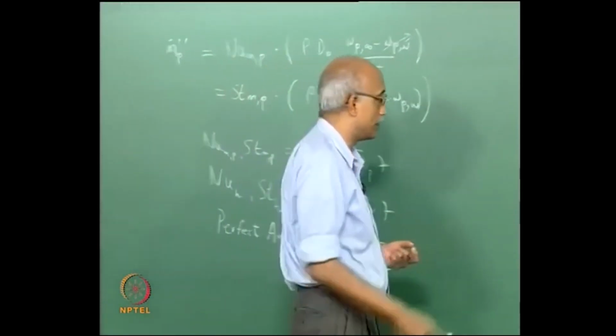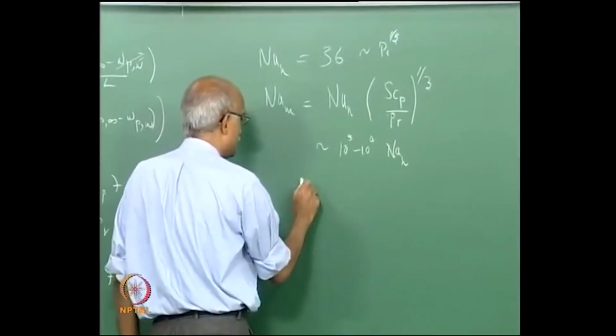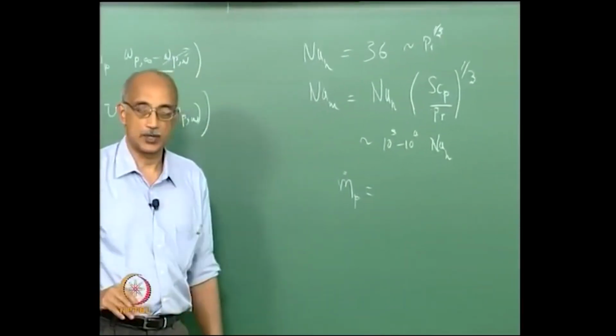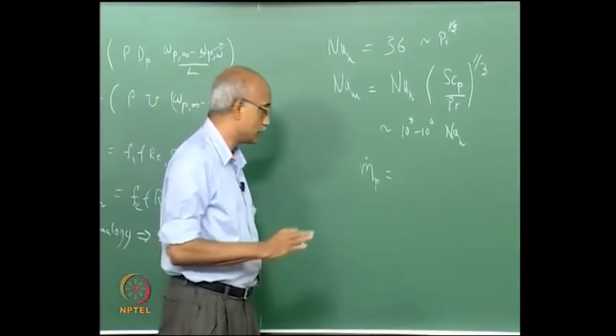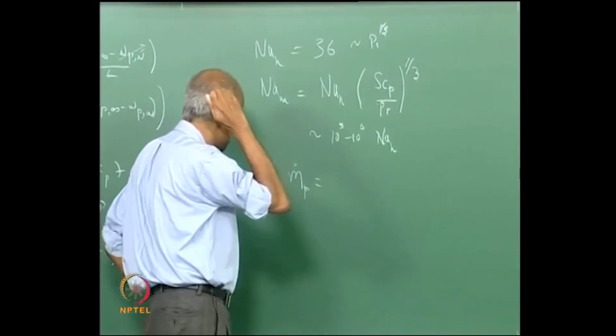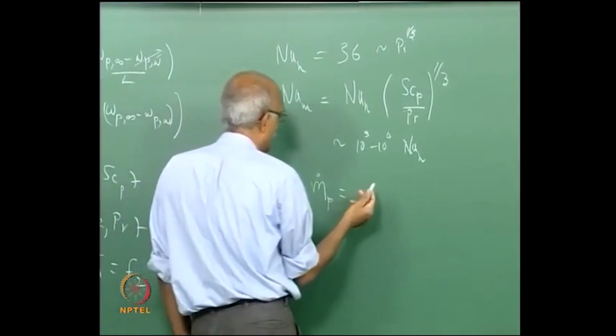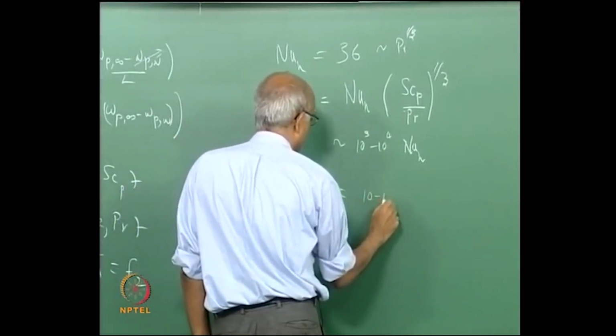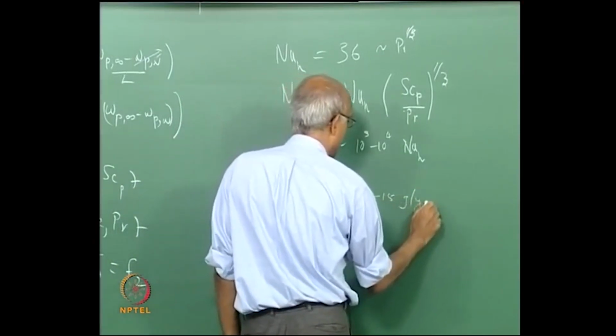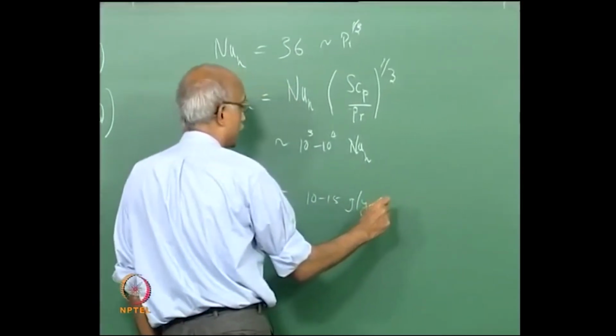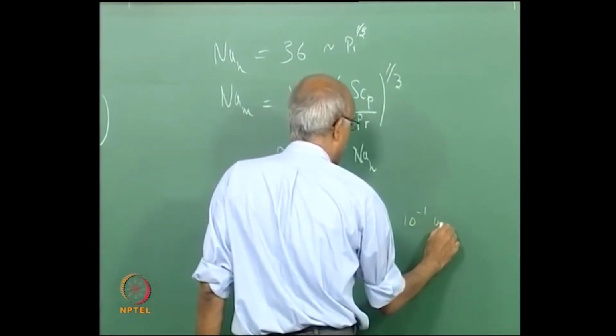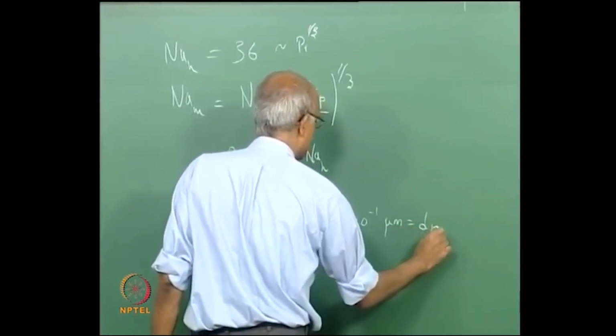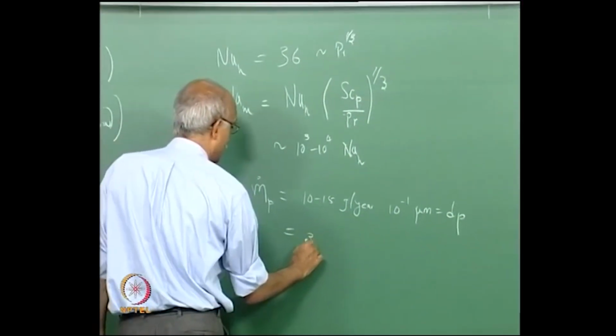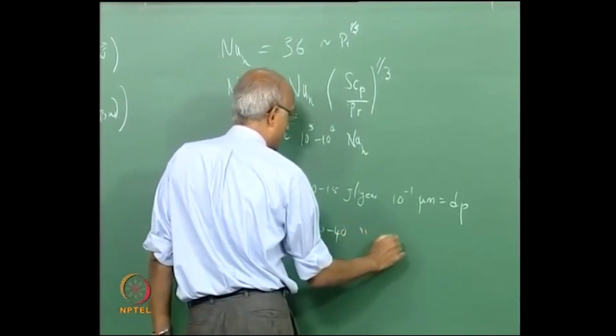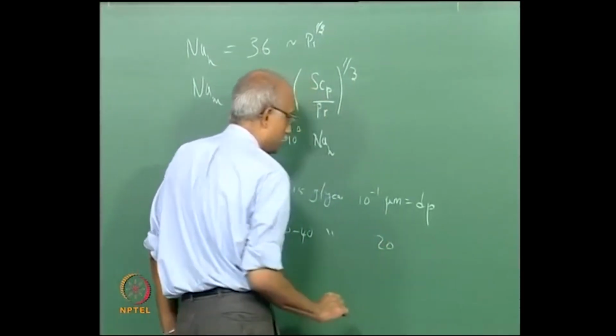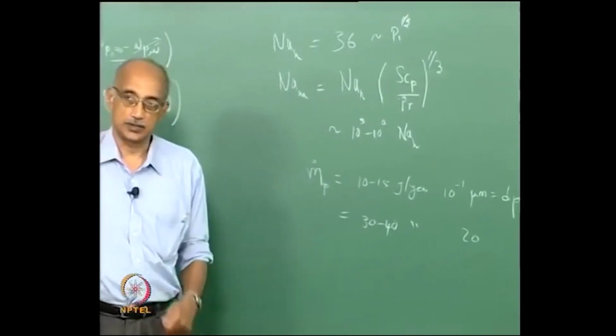That will give you MP dot, the rate at which particles are depositing on the surface, and it turns out to be, under most realistic conditions, roughly about 10 to 15 grams per year for particles in the 10 to the power minus 1 micron size range, and of the order of 30 to 40 grams per year for particles in the 20 micron size range.